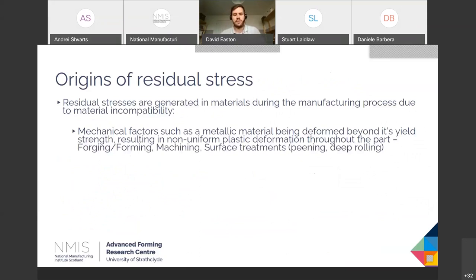So I've mentioned mechanical factors. If we take a metallic material and deform it beyond its yield strength, it's going to cause non-uniform plastic deformation. The part's going to be stretched and it won't return to its original shape. This will cause residual stress. And we see this across all the major forming technologies: forging, forming, surface treatments like peening and deep rolling, machining. All of these are going to introduce mechanical residual stresses.